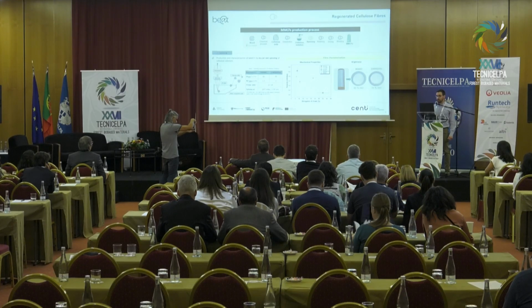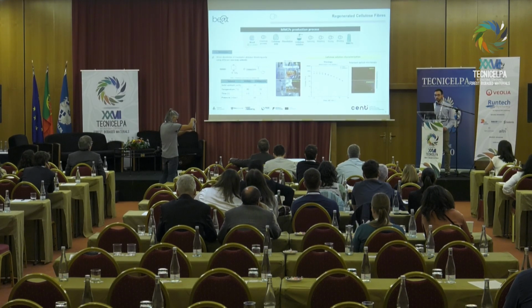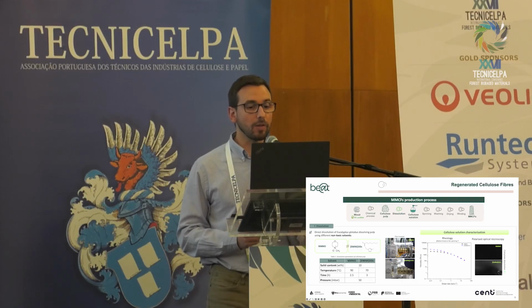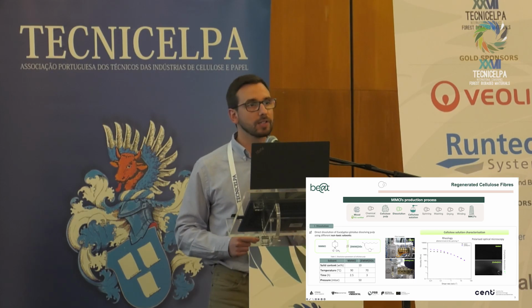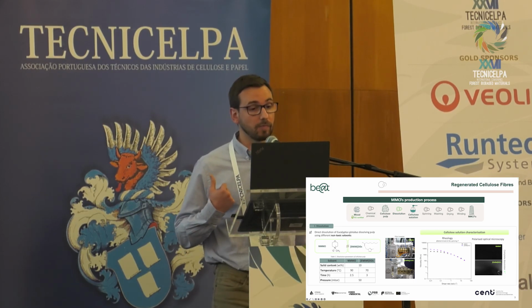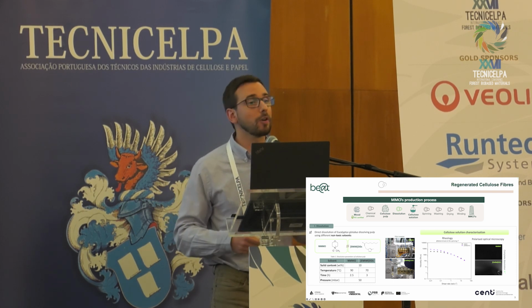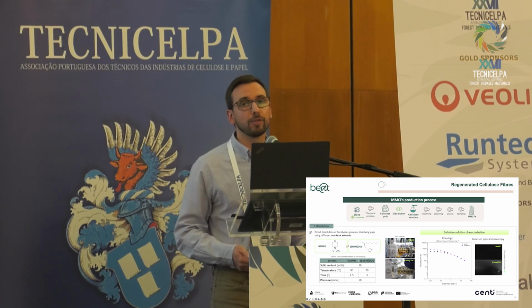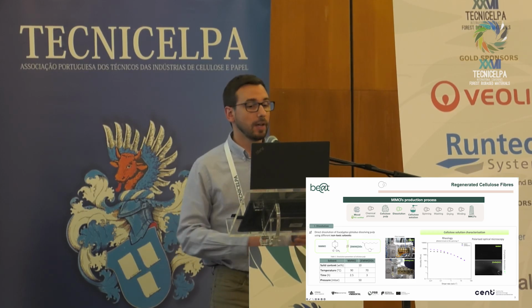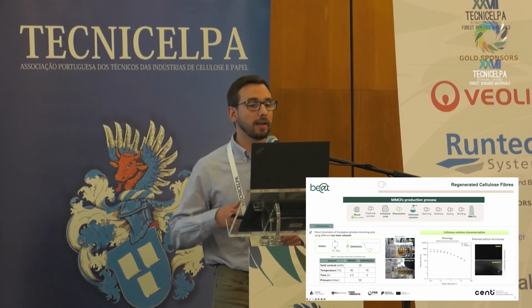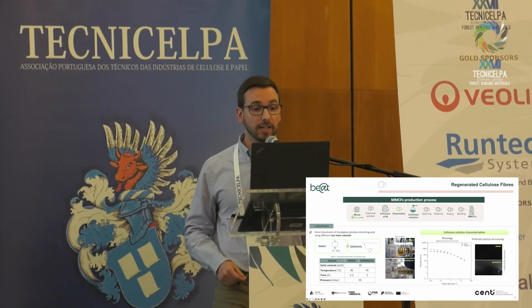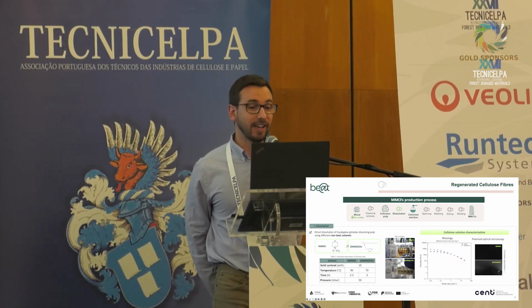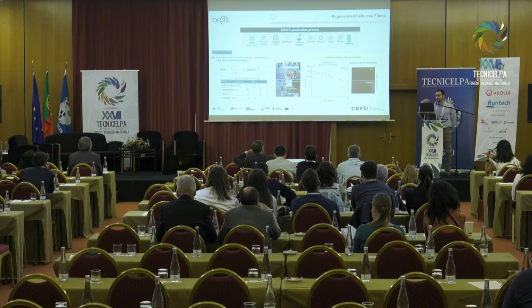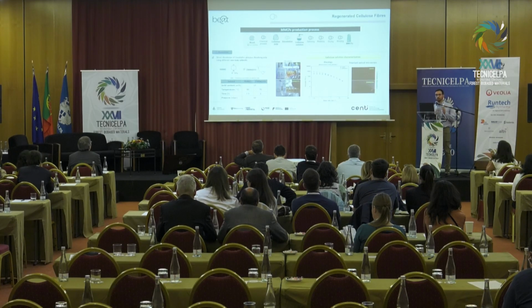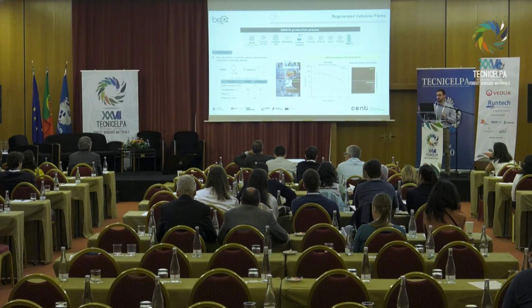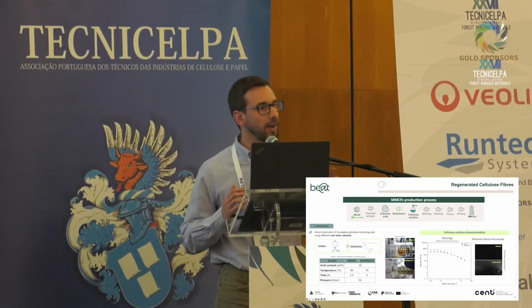Okay, now, what about the results I'm going to talk to you about? What we did was to compare the dissolution using two different direct solvents for cellulose. On one side, we have NMMO, which is a widely accepted and non-toxic solvent for cellulose, which, like many of you surely know, is used in the lyocell process. And the idea was to compare it with an ionic liquid. In this case, this one that you see here, that's pronounced ethylmethylimidazolium octanoate. Yeah, did you get it? Okay. Now, in the end, you'll have to say that to me. And what we did was to compare them in pilot scale. I mean, not bench scale, but pilot scale, not big pilot scale, small pilot scale, still pilot scale, okay?